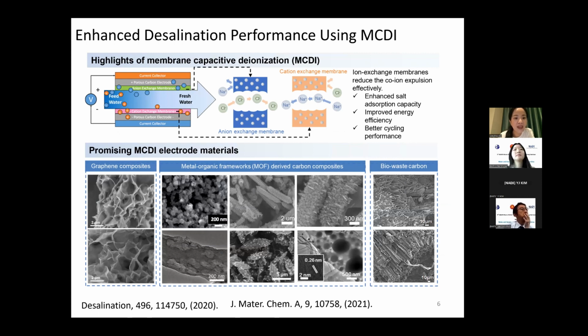And within this design, we have further modified the whole device. We implement a membrane structure. This membrane structure is an ion selective membrane. So we have an anion exchange membrane and a cation exchange membrane on top of the electrode. Those exchange membranes will prevent the co-ion expulsion condition, and that will enhance salt absorption capacity, improve energy efficiency, and give better cycling performance. So we have our group of very promising membrane CDI electrode materials, for example, graphene composite, metal organic framework composite, bio-waste composite, and so on and so forth.